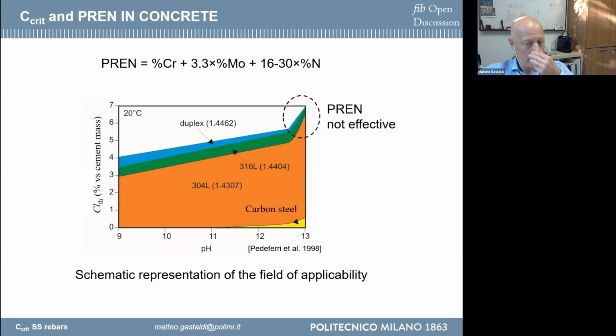So for the concrete that is alkaline, that is in the normal condition that we have, in a structure that is exposed, for example, to seawater, the high humidity that is present in this area doesn't help to have a fast carbonation of concrete, and generally concrete with a low water cement ratio is used, so you have a low penetration of carbonation. It's not so easy to have carbonation at the sea surface, so it's easier to have alkaline condition, and in this condition it's not possible to use the PREN number.